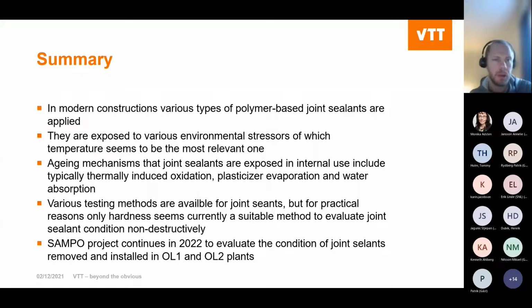So to summarize, in modern constructions, various types of polymer-based joint sealants are applied, and they are exposed to different types of environmental stressors, and temperature seems to be the most relevant one from the aging point of view. The aging mechanisms that joint sealants are exposed to in indoor use are typically thermally induced oxidation, plasticizer evaporation, or water absorption. Different types of testing methods are available for these joint sealants, but currently only hardness measurements could be considered a suitable method when non-destructive analysis of these sealants is considered.